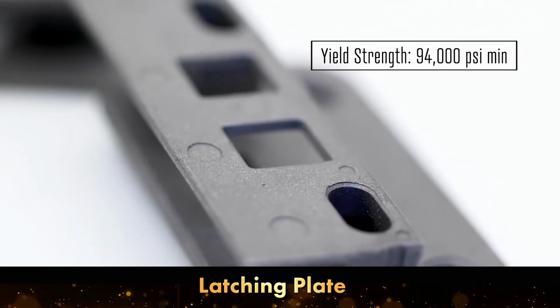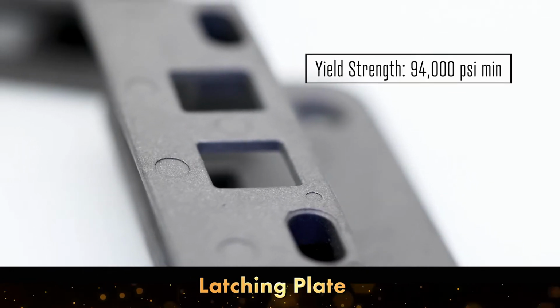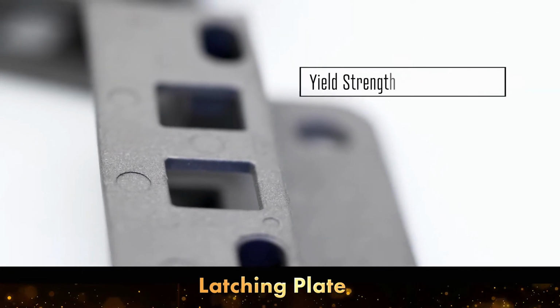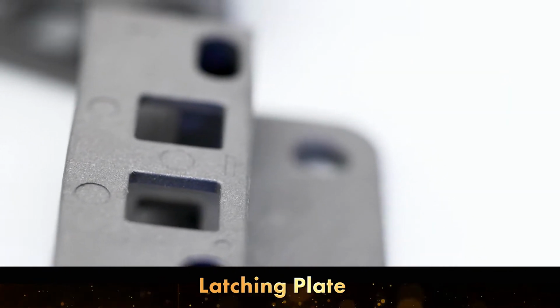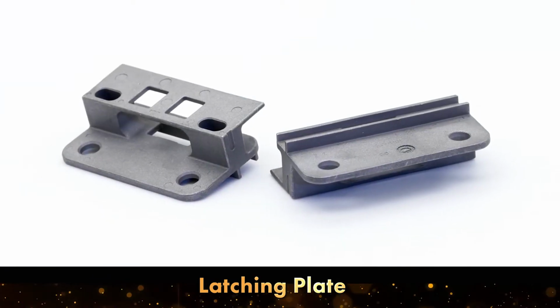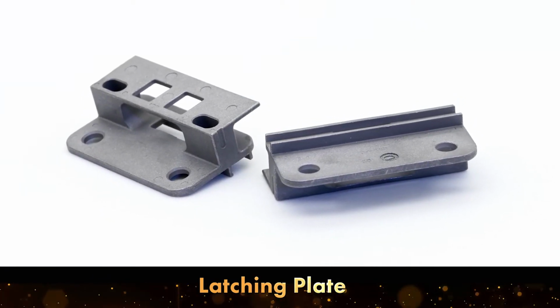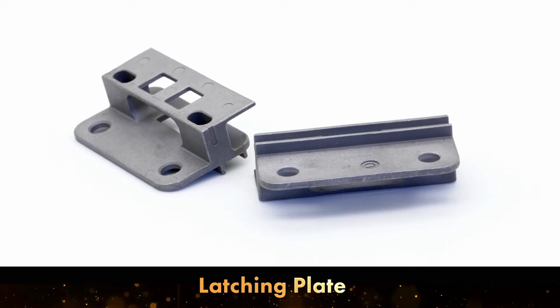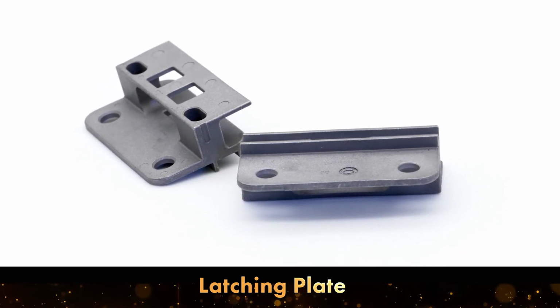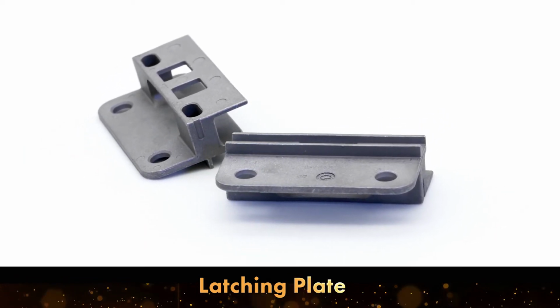A solid film lubricant coating is applied to the part to reduce friction during operation of the collapsible roof. Molding was a challenge, as the part has 2 thin features joined by a thicker slotted section. A well-balanced ejection system used cylindrical and blade ejector pins. Part-specific trays helped minimize distortion during sintering.